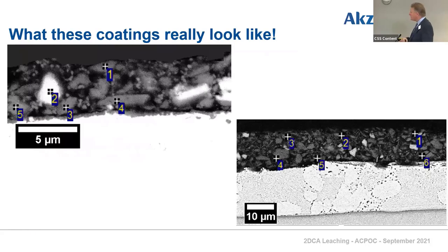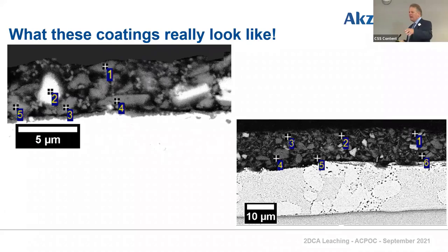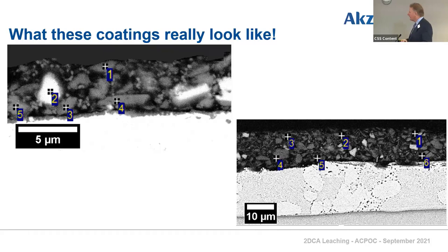What do our coatings really look like? This is a cross-section for a couple of coatings. As you can see, these pigment particles are really quite random. We put in a particular material that gets mixed with a solvent and a polymer, and it goes through a high-shear mixing process that will break up the particles. So even if we try to put a particular type of particle in, the particle incorporated in the coating will look quite different. These are two coatings at different stages of milling and different magnification, where you can see different sizes of particles.